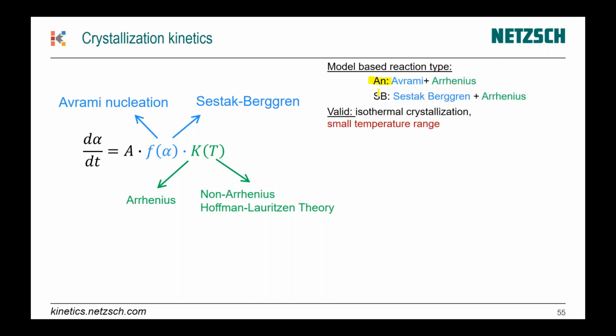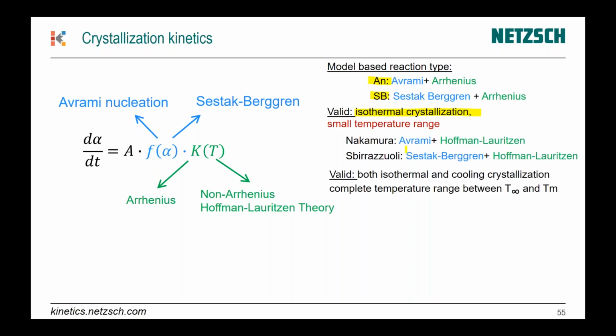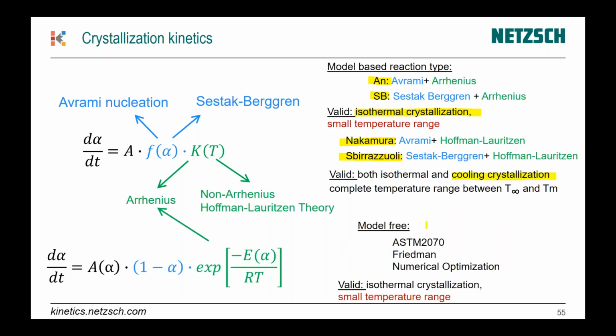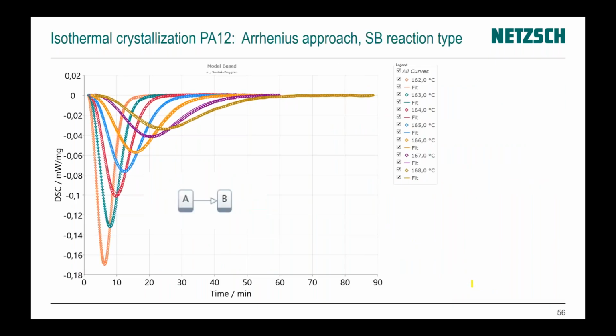It is Avrami plus Arrhenius, Sestak-Berggren plus Arrhenius - they both work only for isothermal crystallization. Then Avrami plus Hoffman-Lauritzen is the Nakamura model, and Sestak-Berggren plus Hoffman-Lauritzen is the Sbirrazzuoli model - they work for both isothermal and cooling crystallization. And of course we have some model-free methods, which work only with the Arrhenius approach and only for isothermal crystallization.